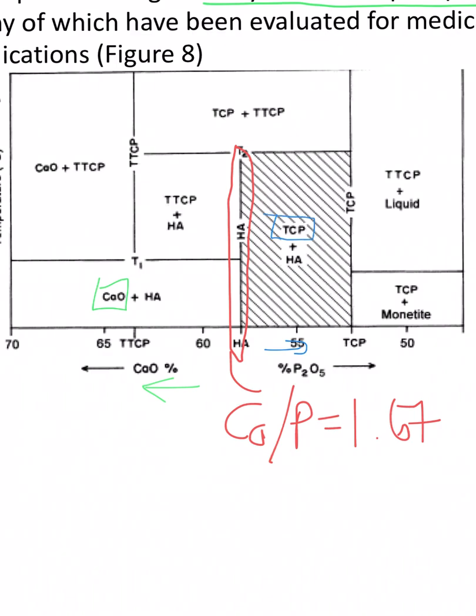Okay. Does anybody know anything about calcium oxide? Any familiarity with that? So we put calcium oxide in water, what happens to it? Anybody? That's calcium carbonate you're thinking of, but that's a good catch. Calcium oxide in water turns into calcium hydroxide, which generates a pH of 12. Okay, so that's not good for the body, which should be pH 7.4. So you put calcium oxide in the body and make calcium hydroxide, pH of 12, things start dying pretty quickly.